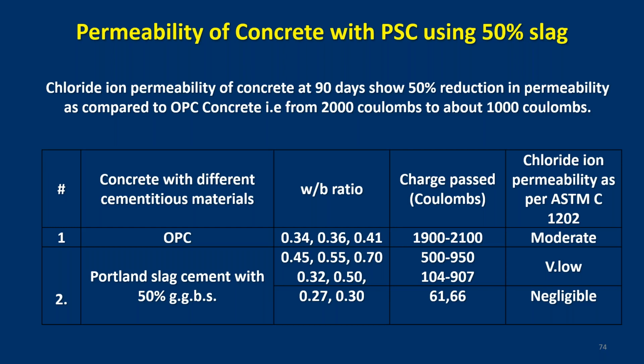With 50% slag, so this one is OPC, there are certain concrete tests, OPC with the water cement ratios 0.34, 0.36, 0.41. You see the coulombs we got is between 1900 and 2100. With 50% replacement, we got a very small number of coulombs. That is because of this GGBS, a supplementary cementitious material, which means pore refinement by the GGBS.